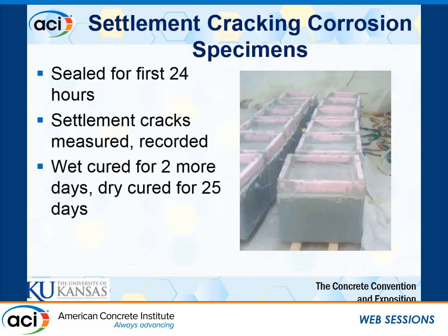So getting back into our finishing and curing procedures, when we cast our settlement cracking specimens, we place a slanted, elevated piece of plexiglass plate over the top of those and then seal that with a sheet of plastic over the top to make sure that we're not losing any moisture or creating any other threats from plastic shrinkage cracking, isolating settlement cracking by itself. And we're leaving that surface undisturbed at the same time. So 24 hours after casting, we record the crack length and width directly over the rebar.